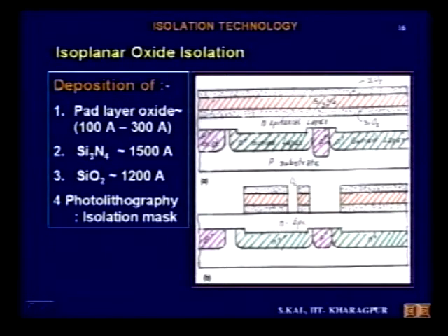Okay, and with the photoresist layer you can remove the top silicon dioxide. After removing the top silicon dioxide, you remove the photoresist. Then you dip the whole thing in silicon nitride etchant, and in this region the silicon nitride will be etched, but here it will be protected by silicon dioxide. Silicon nitride will not etch.